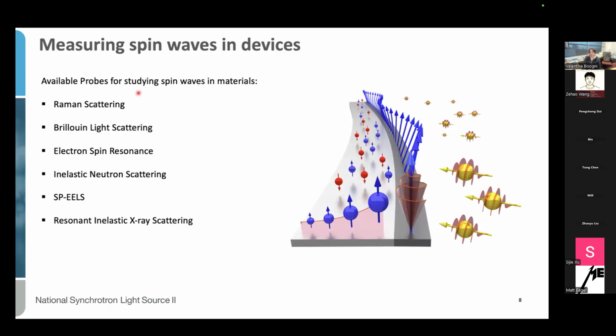So normally when we want to measure magnons, we can deal with a long list of techniques that give access to this information. And here I'm just listing the major ones like Raman scattering, Brillouin light scattering, electron spin resonance, inelastic neutron scattering, spin polarized EELS, and resonant inelastic X-ray scattering. So next, if we are interested in the energy versus momentum dispersion, we basically get rid of the first three techniques as they are limited to momentum zero or very close to zero.